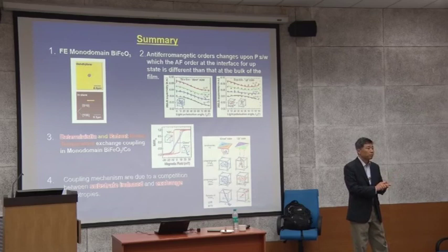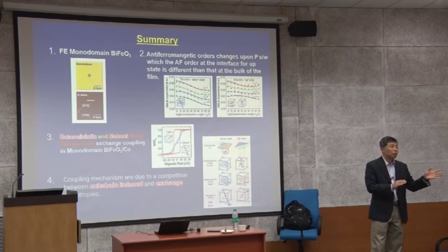Before going to PFM, we should test the device also. I mean, it should not break down. That's actually better. And then for the electrical measurement, you know the ferroelectric tester? Yeah, measure the P loop. You know what the saturation is and how much field you need, and you can actually see that. And then that is the first approximation for the PFM measurement.